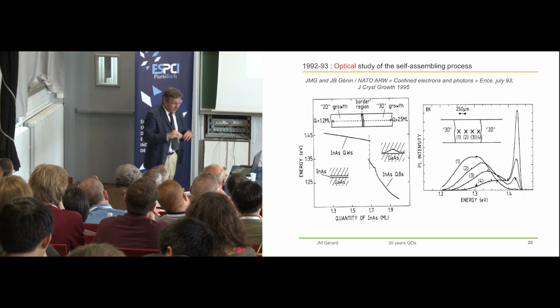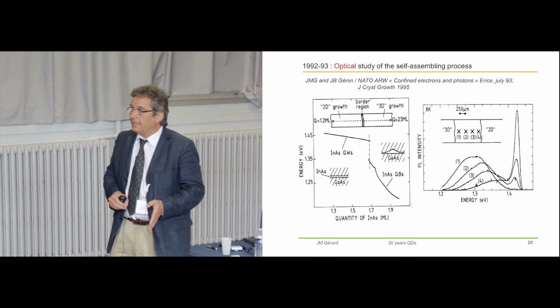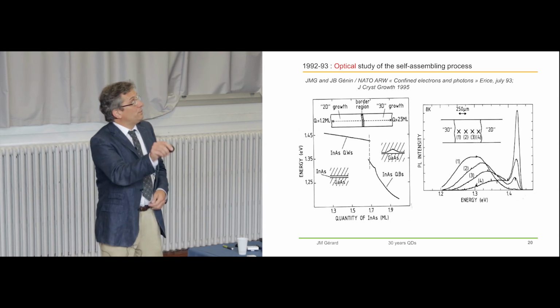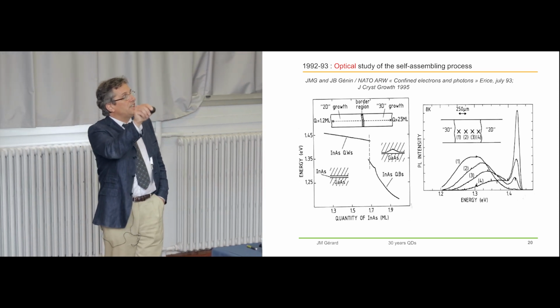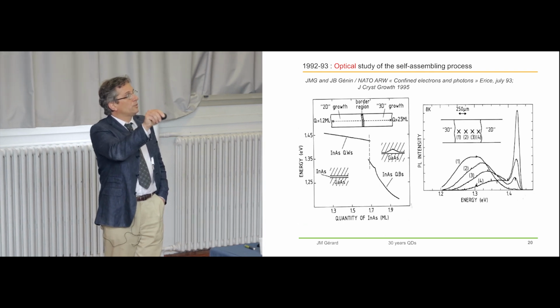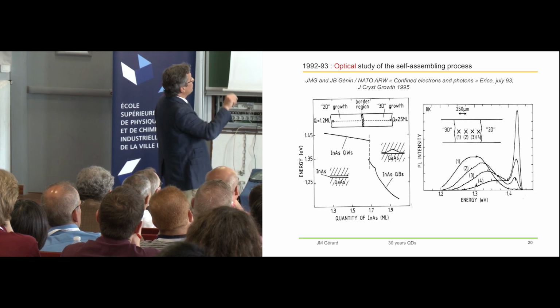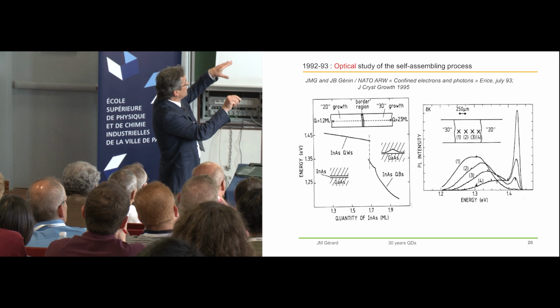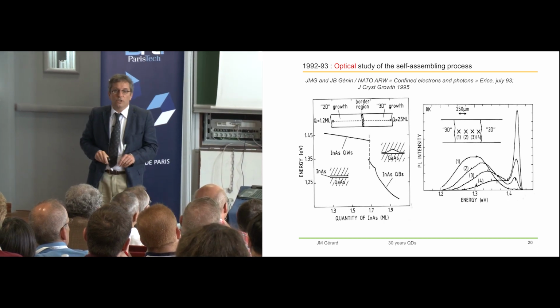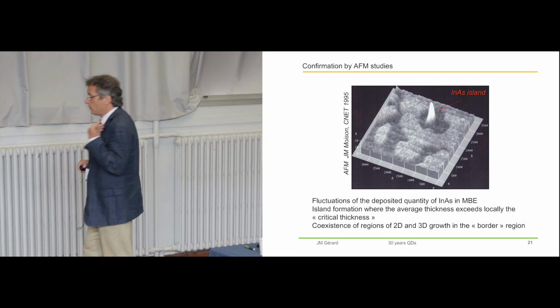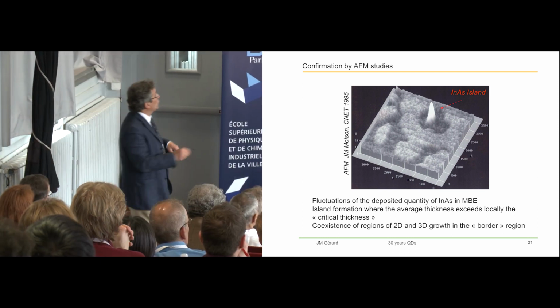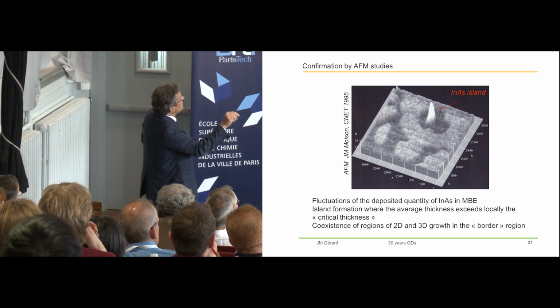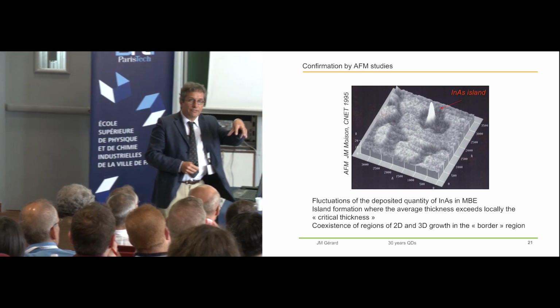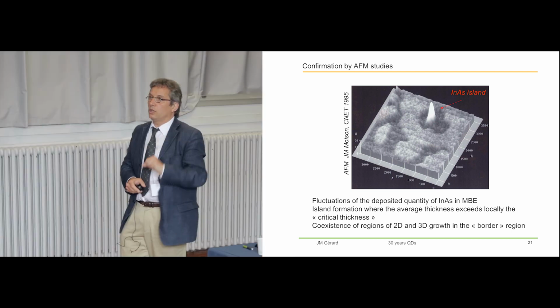In fact, the first thing you see when you do that is that the border is not a line. The border is a region. And in this region, you observe both the signature of 2D growth here and of quantum dot formation here. And when you go from the 2D region to the 3D region, you simply decrease the intensity of the 2D signal and increase the intensity of the quantum dot signal. This tells you a lot. What you learn here, and which is confirmed after that by AFM, is that you have on the surface coexistence of regions of 2D growth with plus one monolayer fluctuations, and regions where the quantity of indium arsenide has been enough for the growth of one quantum dot to occur.